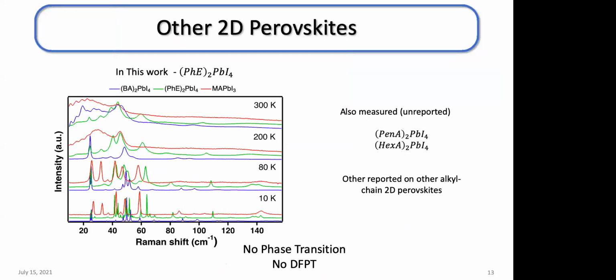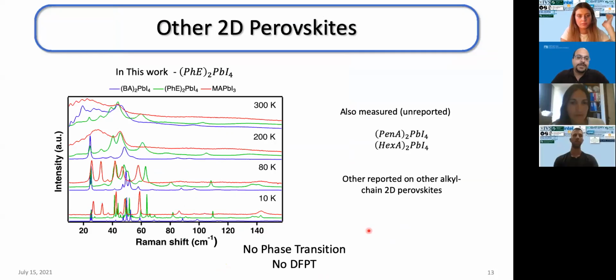Yes. So in general, you can see my slide right there. We have measured another perovskite, which I left out of the presentation. It's phenethyl ammonium lead iodide, where the organic cation has a conjugated molecule, and the interactions between organic molecules are much stronger. What we have seen in the Raman is that it exhibits no phase transition, and its symmetry is much, much lower, telling us that as the interaction increases between the organic molecules, it reduces the symmetry or dictates more the symmetry of the crystal and denies phase transitions, for example.